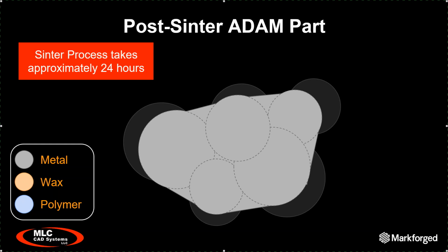It takes about 24 hours to heat, hold, and then cool the parts to where you can work with them. But the polymer, the gaps held together by the polymer, that is where the gases escape, through the holes that the polymers were holding together. And at the end, you're left with a 99% plus dense part made of metal with no residual effects or even memory of where it came from or how it got there. The only thing that will indicate that it used to be a bunch of metal powder is that you'll see the layer lines from the printer process on the perimeter, and there's a sparse fill inside. Otherwise, it's a solid metal part like any other.